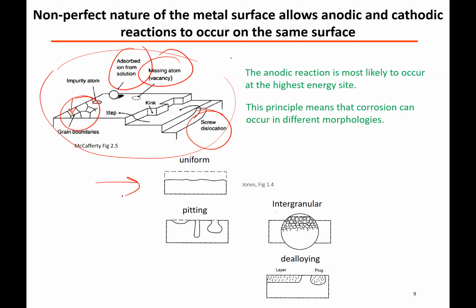And you can have uniform corrosion. So this is across the board, where all your sites are evenly distributed like this. Then you can also have corrosion where it pits. So basically, you have these voids that can form due to non-uniformity in the material. And interestingly, you can use that to your advantage. You can use it to dealloy a material, let's say. So if you have copper and magnesium, something like that, or silver and magnesium, whatever, what you can do is make that alloy, and then you can etch away, corrode away the magnesium, say, and then leave these pits.